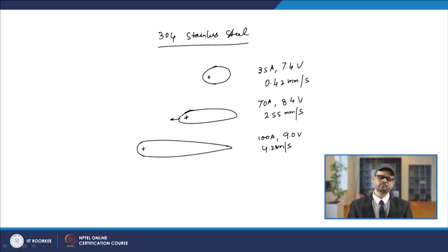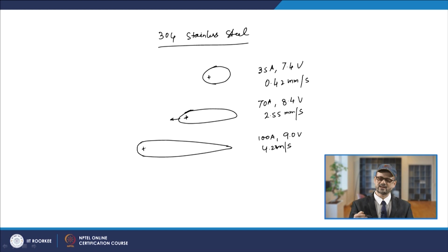Now, if you do it for the stainless steel and if you do it for the aluminum, you can see it more visibly in the case of stainless steel, because aluminum is more conductive. So, there has been a certain observation, with a particular heat input and also the velocity, especially at larger velocity, that a sharp pool end was seen in the case of stainless steel. It is because of the larger velocity that the larger velocity will give you such kind of pool shape.